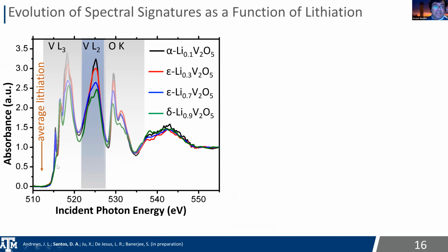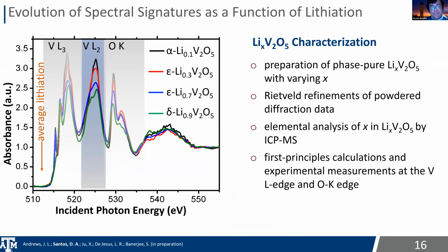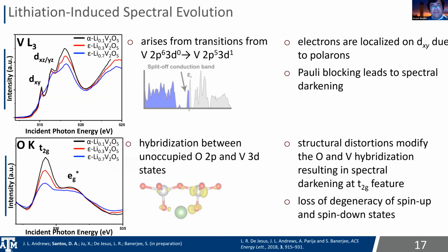So this dxy peak, which is the split-off conduction band here, is decreased in intensity as you lithiate more and more, okay? And we've got some beautiful high resolution spectra. Again, the work of Justin Andrews and David Santos, really looking at these spectra. We can see that the dxy peak weakens, and so we've got some really great standards that we can assign any spectral data sets to, right? And so you can see here the dxy bands diminished.